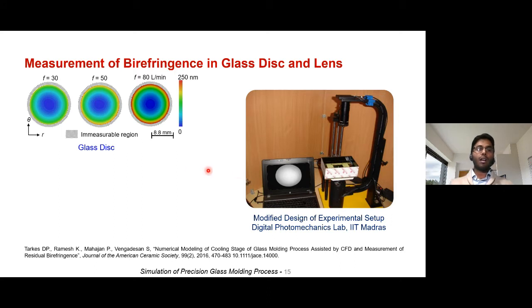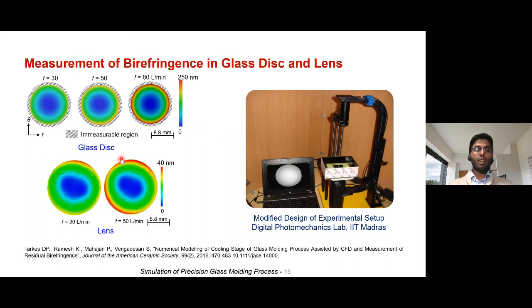And these are the set of results for the glass disc. What you can see here is a very nice axisymmetric distribution of residual birefringence. And from this, there was an input to the finite element simulation that we could make as a 2-dimensional axisymmetric simulation. You can see that the birefringence values are quite high, because the nitrogen gas is directly interacting with the glass disc during the cooling stages, and there is a high amount of residual stress. That is what you see here at 30 liters per minute. As the flow rate is increased, the residual birefringence increases. Similarly, we did the experiments for the lens, and you can see that for 30 liters per minute you have very low birefringence, and for 50 liters per minute you have a little bit higher birefringence over here. So this is for a plano-convex lens.